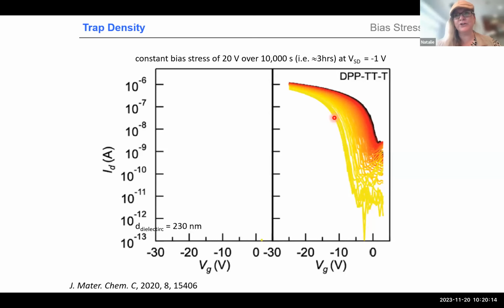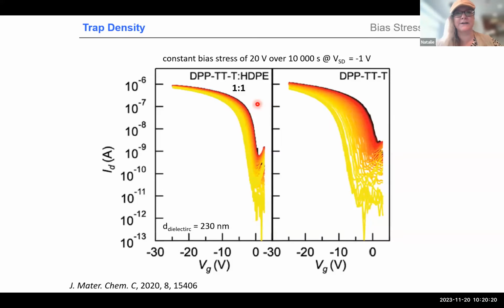To be fair, this is not only a problem of organics, it's actually really, really pronounced with silicon, amorphous silicon. Once we add polyethylene, you see this is much less pronounced. And usually people believe bias stress comes when you have traps in your material. So this really indicates that indeed polyethylene helps to reduce traps in our system.